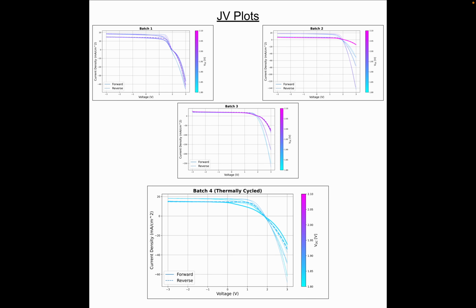And VOC is called open circuit voltage, and it's generally proportional to power conversion efficiency. Kind of shows the potential of the cells. And so some of the first batch that we've made here, and this is a very new, novel idea to use perovskites in space because of their degradation factors. And with this JV in our preliminary findings, we saw certain discrepancies and damages. They didn't look perfect, but we saw very strong results as a whole.